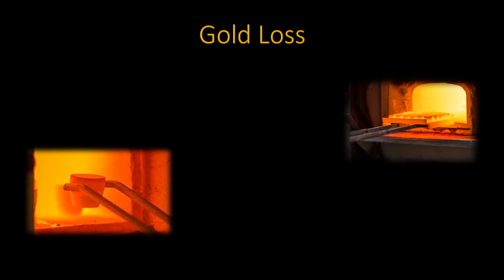The loss of gold can and does happen. This loss is in direct relationship to temperature. At temperatures greater than 900 degrees centigrade, gold loss increases. Below this mark, losses are very low.